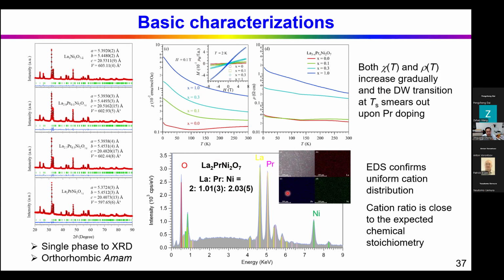But this polycrystalline sample is pretty homogeneous. According to this SEM and EDS measurement, we confirmed the uniform distribution of the cations, and the cation ratio is very close to the expected chemical stoichiometry. For example, for this lanthanum 2 praseodymium 1 nickel 2 sample, the ratio is 2 to 1 to 2, so it's very close to the starting ratio.